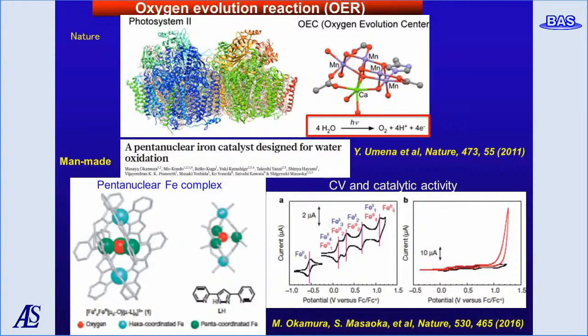Recently, a pentanuclear iron complex consisting of 5 iron ions linked by a nitrogen-containing bridging ligand has been synthesized, and the redox behavior was clarified by cyclic voltammetry. As shown here, 5 reversible redox waves corresponding to iron 2 to 3 were observed in the voltammogram.